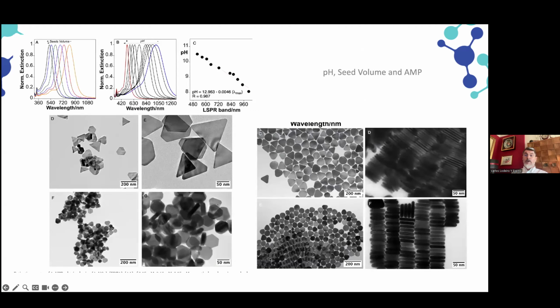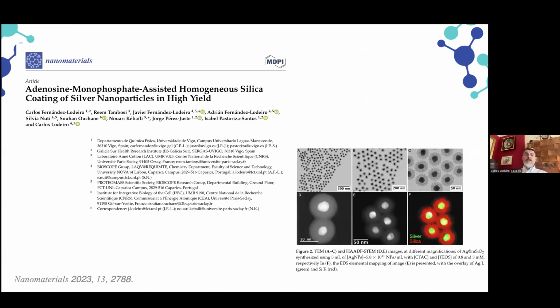So they are very monodispersed. I can show you here in these pictures of transmission electron microscopy that just playing, for example, with the pH, we can control in this case the plasmonic band and then the thickness of the nanoparticles. They are pretty well organized, as you can see in panel F, in which each plate is connected over the other, and then also changing, through these supramolecular interactions, the photophysical aspect of our nanoparticles. So maintaining the same synthetic approach using the adenosine monophosphate, we can also create nanourchins.